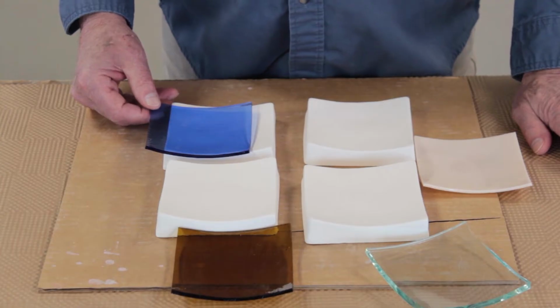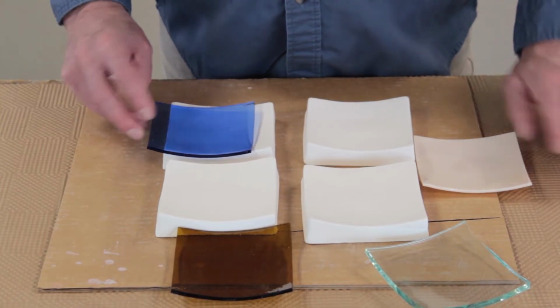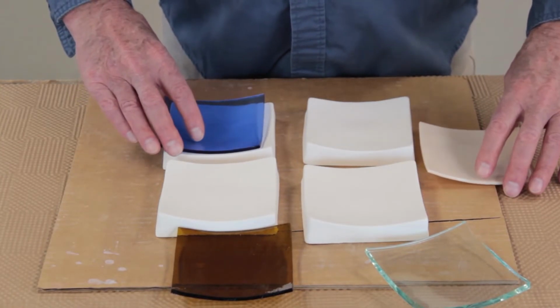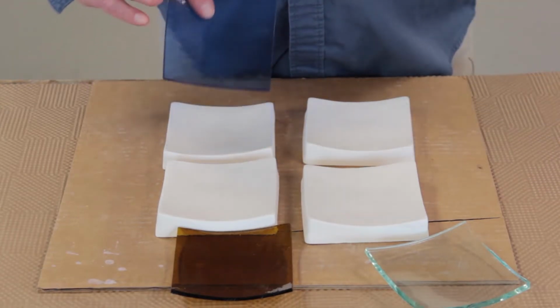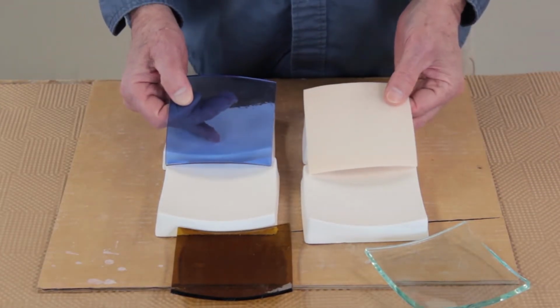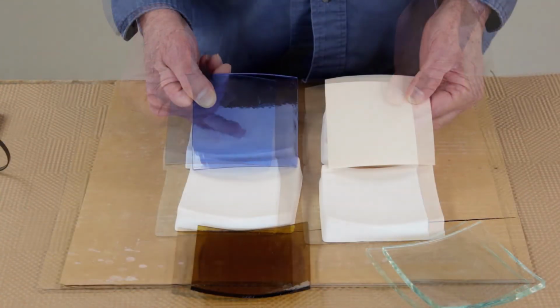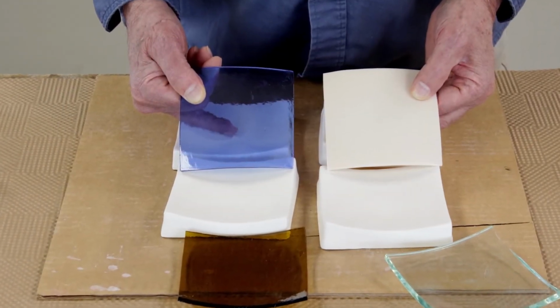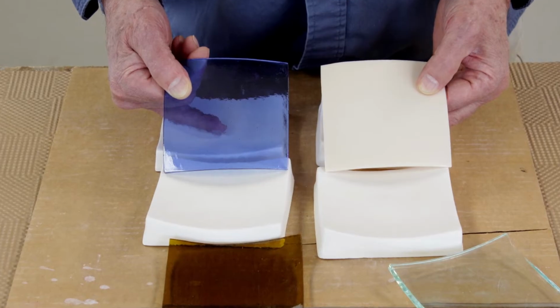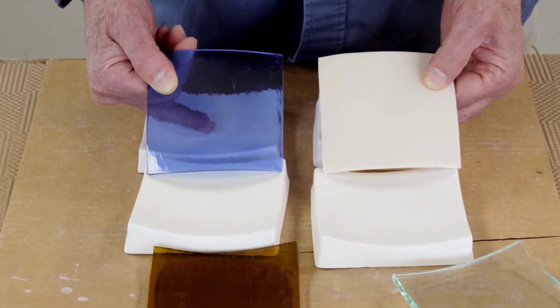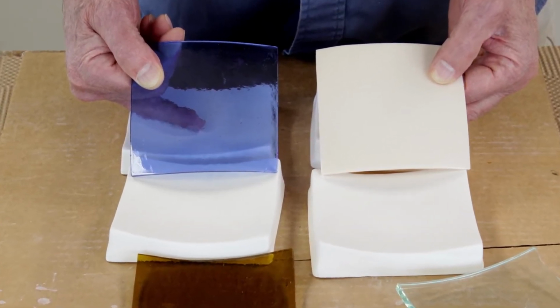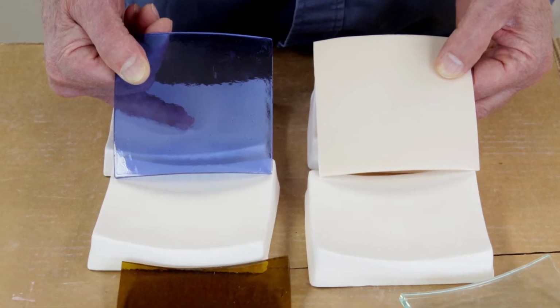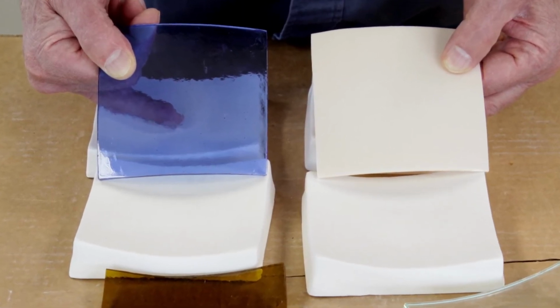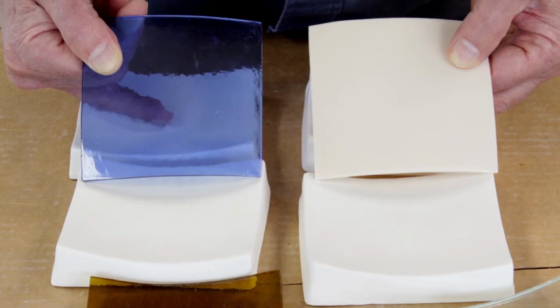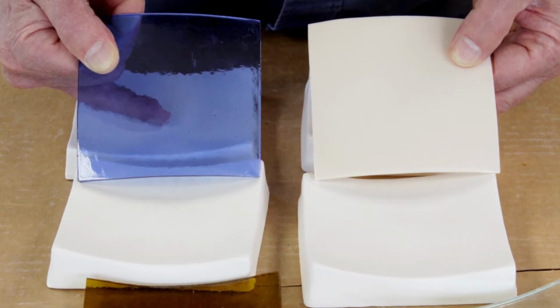Now, what's really interesting about these projects is that not only did they not need any kiln wash, but they came out with a perfectly smooth underside. The glass was fired direct onto the ceramic molds. There was no kiln wash, no boron nitride, no kiln paper, nothing. Just the bare mold. Not only did the glass not stick to the mold, but it came out perfectly smooth without any of the texture that would have been picked up if any of those had been used.